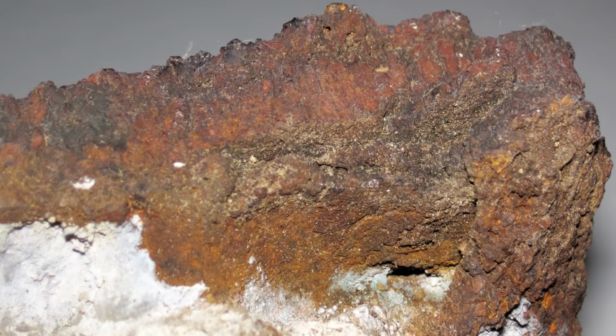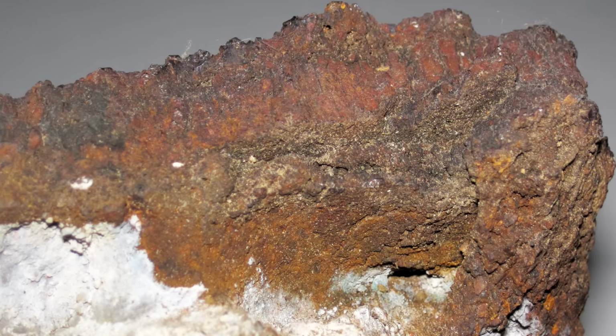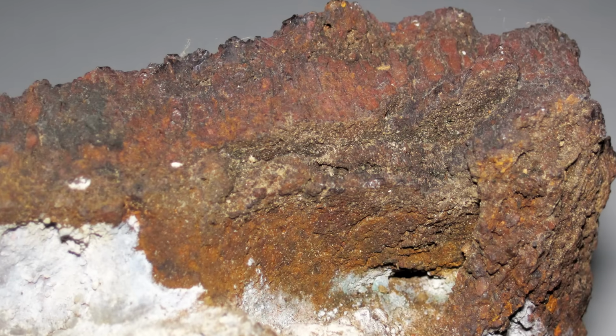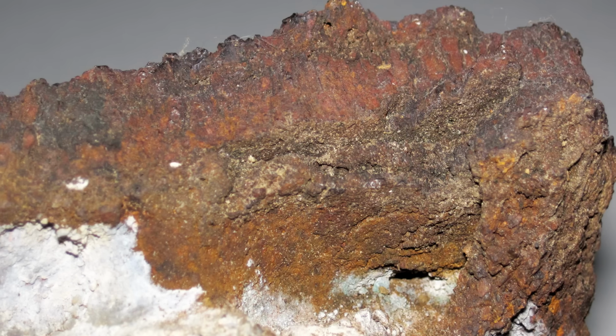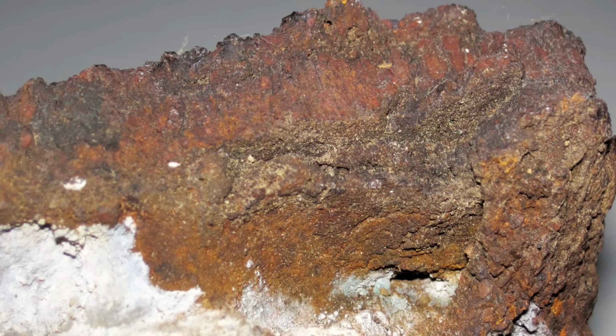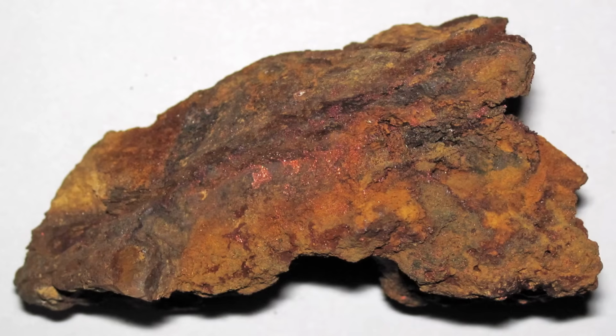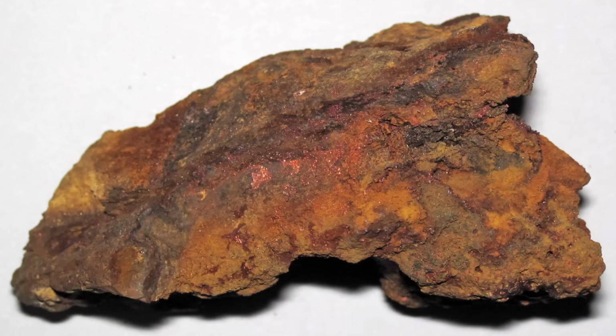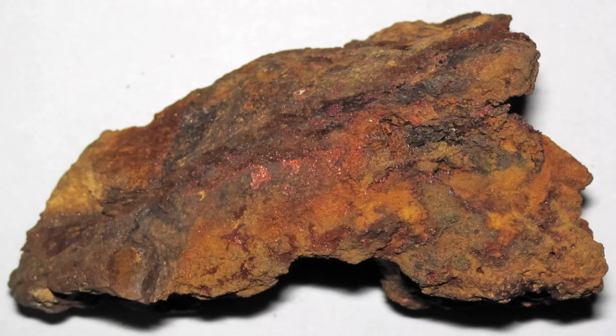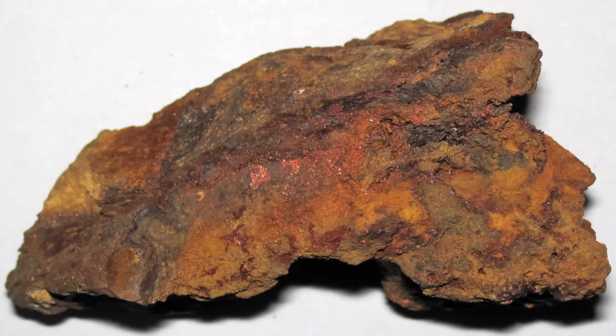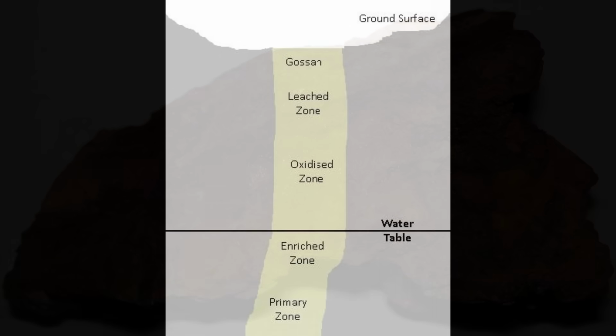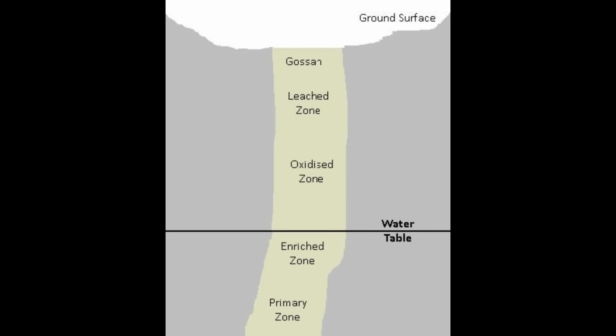And that's where the probability shifts, because gold doesn't form randomly, it forms in systems. If you can identify that a system existed, and that it carried sulfides, you've already done most of the work. The iron is just telling you that the upper part of the system has been exposed and oxidized. But here's where things get even more important. Not all of the system is oxidized. Below the oxidation zone, sulfides often remain intact.